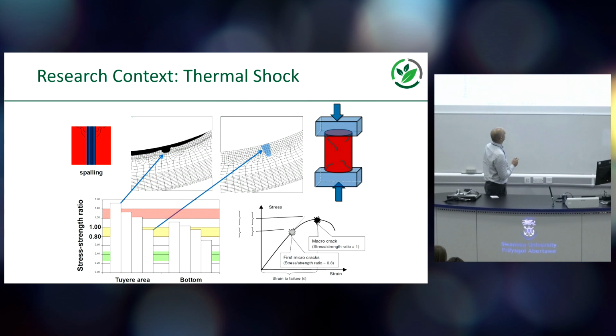And one of the main reasons that you will get wear is a process of thermal shock, where, because these are transient processes, we fill and then we empty a ladle, for example. Refractories can heat up and cool down relatively quickly, and that creates micro cracks in the surface, which are then exploited either through thermal shock or a combination of thermal shock and chemical degradation, as we're going to see later on when we talk about gases other than natural gas. And then that can lead to a reduction in the strength of the material and rapid degradation of the products.